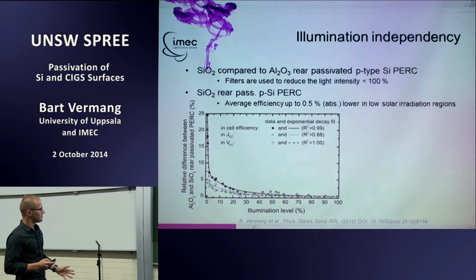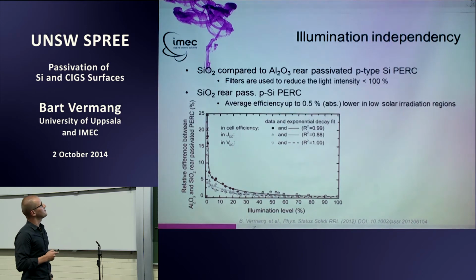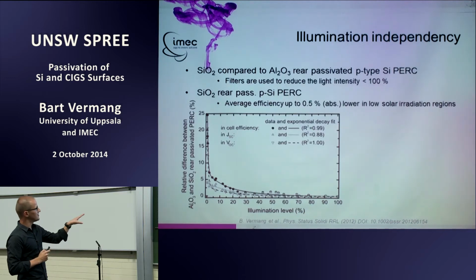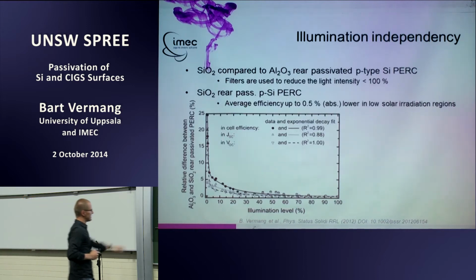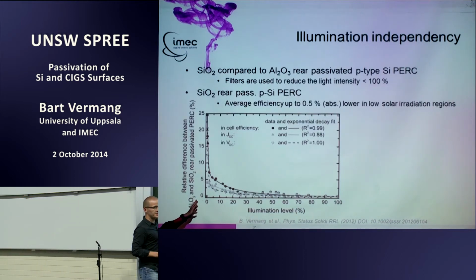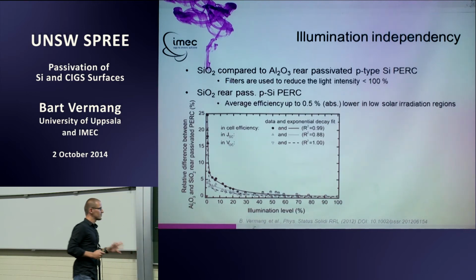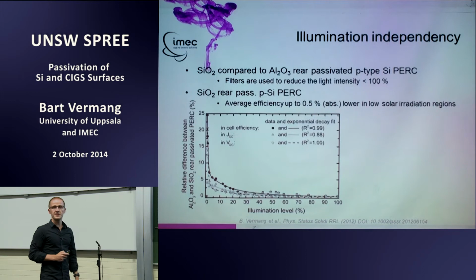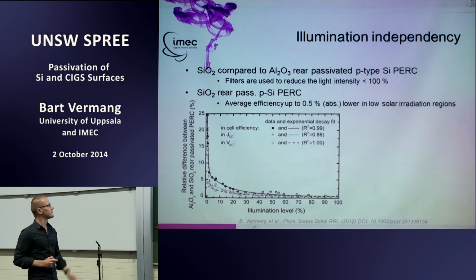And we've tried to measure this, or we measured this by using filters for silicon oxide or aluminum oxide rear-passivated silicon PERC cells. And here you see the difference between aluminum oxide rear-passivated and silicon oxide rear-passivated as a function of illumination level. And you see VOC, JSC, and cell efficiency. And the degradation or the difference is really within the silicon oxide rear-passivated. So there you see a quite large illumination dependency due to a loss in JSC and VOC at lower illumination. That's also an advantage of having aluminum oxide as a passivation layer on P-type silicon.